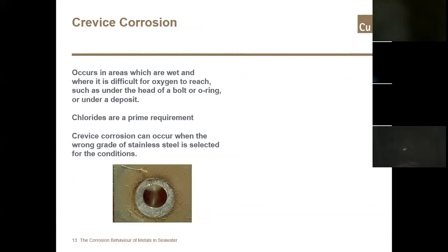Crevice or under-deposit corrosion can also be an issue where the oxygen becomes locally depleted. An electrochemical cell is created where the film may have broken down, exposing the metal below, which then becomes anodic compared to the adjacent material, and the steel will then corrode. Crevice corrosion occurs more readily than pitting in seawater and at lower temperatures. So higher levels of the same alloying additions are used to improve resistance to crevice corrosion as well as pitting. Molybdenum, nickel and chromium all add to the corrosion resistance.